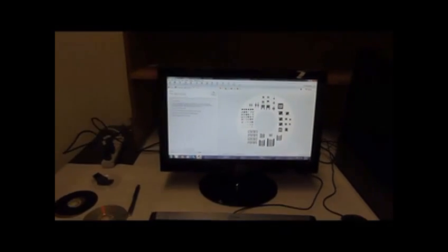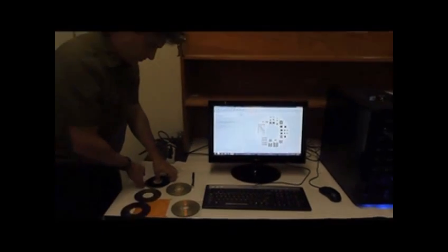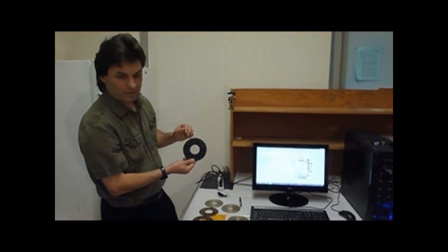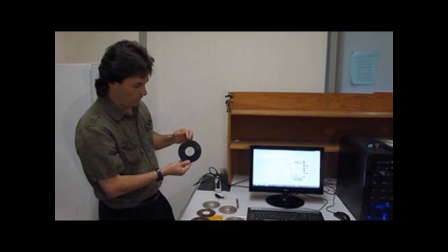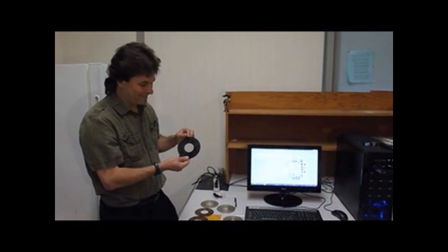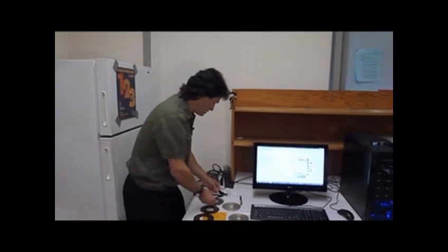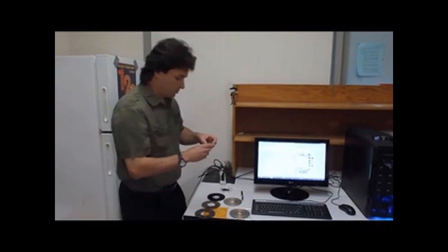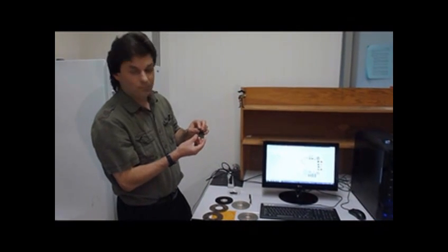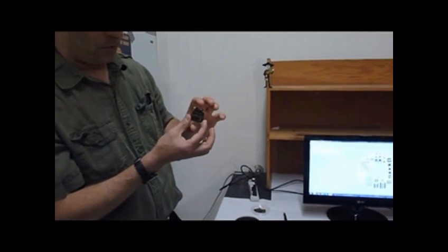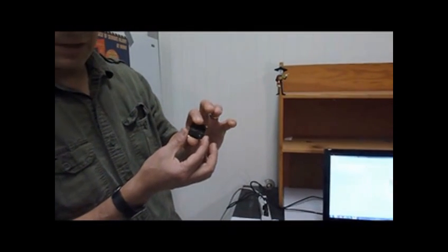We can do this with thin materials, or we can do it with thicker materials. And so, for example, here's a thicker coating of our graphite oxide that's been laser scribed and turned into graphene. We can take this then and just cut it with the scissors, and we can make different devices. And one of the devices that we've made is a supercapacitor. It's a flexible, all plastic-based supercapacitor. It's just two pieces put together with a little electrolyte. You can see it's completely flexible.